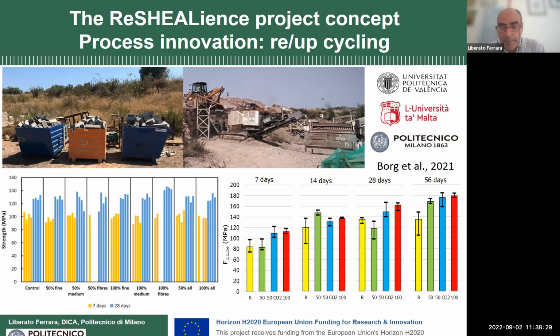And these materials, because of their peculiar content, mix design, content of cement and so on, have a high recyclability potential, because you can see here, if you compare the yellow bar chart, which is the reference material, all made with new constituents, with the green, the blue, or the red, in which we replace respectively 50% in the green or even 100% of the natural aggregates with recycled ones, you can see that we have no decay of the performance. And we also tried to artificially carbonate some of the recycled aggregates to see whether this environmental exposure was affected. And also in this case, we had no decay of the performance.